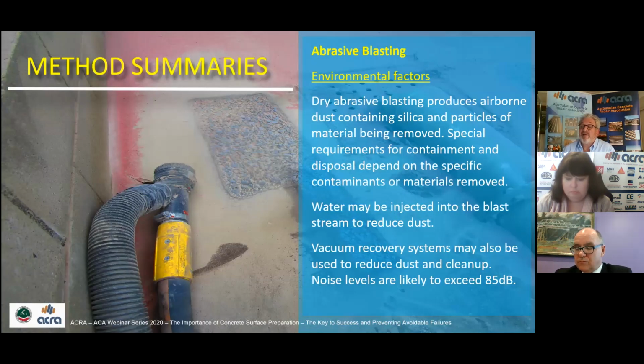The environmental factors relate a little bit to what Martin presented last week. Dry abrasive blasting produces airborne dust containing silica particles, and also the material being removed. You have to look at containment and disposal, depending on what's being removed. You can inject water into the blast stream to reduce dust, or you can use a vacuum recovery system. Noise levels generally exceed 85 decibels.